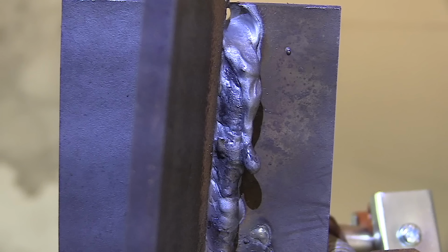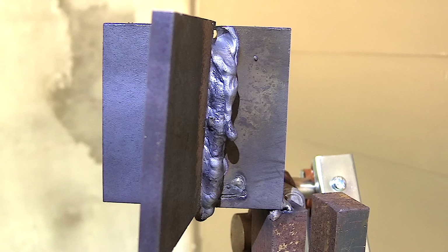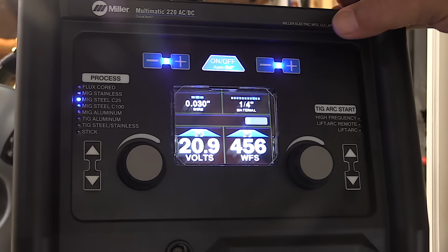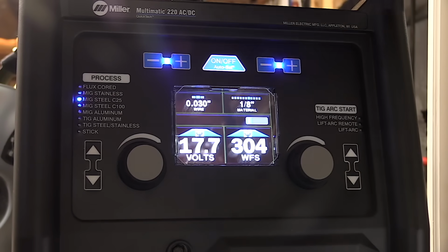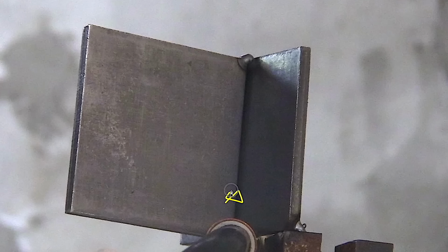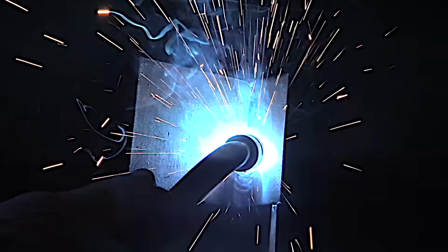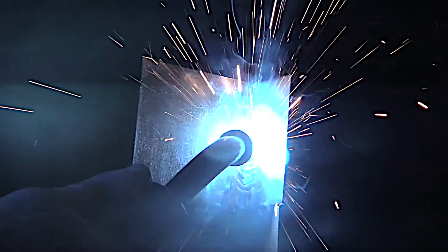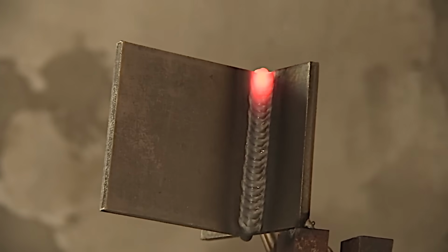So what I do is I pick a setting about 1 or 2 metal thicknesses lower, still using the chart, but then also using a little technique like this little triangle technique, which steps me forward and still keeps the arc on the leading edge of the puddle, keeps me burning into the root of the joint, helps the metal spread out a little bit, gives me a little pattern for some uniformity, and makes a decent looking vertical uphill weld instead of one that falls out on my boots.